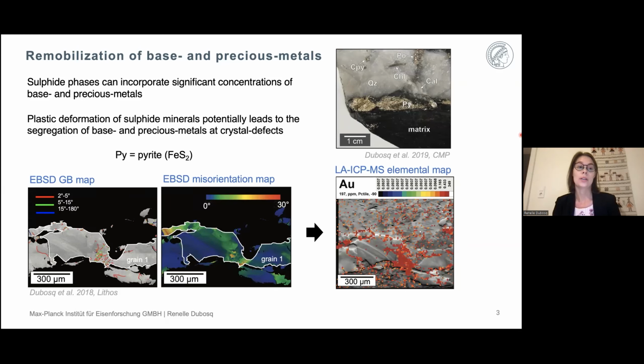One of these studies was actually my master's thesis project, where I combined EBSD mapping and laser ICP-MS elemental mapping on a deformed pyrite crystal from a gold deposit in Canada. Here at the bottom of this slide, I show EBSD grain boundary and misorientation maps of a pinch and swell structure within a pyrite grain.